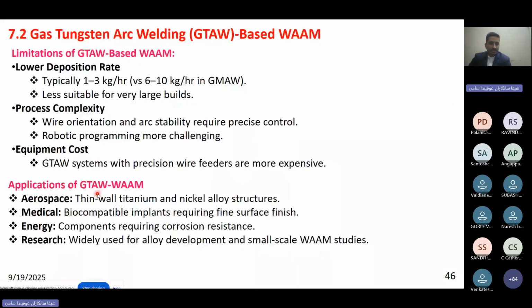Okay, of course there are some drawbacks. The deposition rate will be somewhat lower. For example, 6 to 10 kg per hour can be achieved in the gas metal arc weld based WAM technique, but here 1 to 3 kg, and it is less suitable for very large builds. There is also process complexity because we need to synchronize the wire, gases, and welding torch. And equipment costs will also be high.